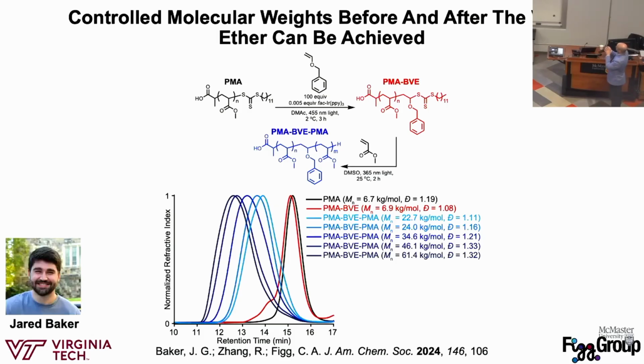But what's really interesting is that I show this step where we're going from a benzyl vinyl ether to a methyl acrylate polymerization. This looks really easy to draw on paper. It's just like a RAFT polymerization of methyl acrylate when you first look at it. But I could draw anything in ChemDraw and say this is going to work really well, right? This is actually really challenging and goes against the way that RAFT polymerization is designed. So we're going from this benzyl vinyl ether, which is a pretty high energy radical, and we're going to try and chain extend it with this methyl acrylate, which is a relatively more stable radical than the benzyl vinyl ether.